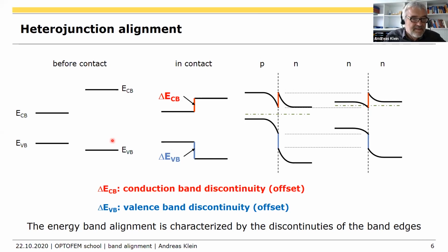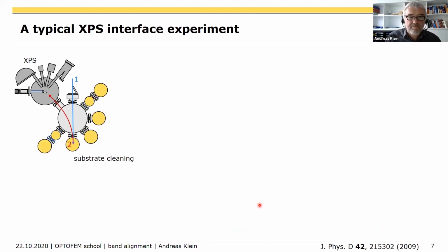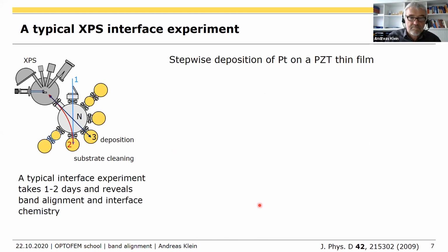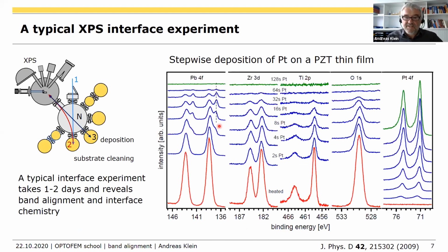Question by Pamela: on slide 7, what is the approximate thickness of platinum to induce a clear reduction of lead? Well, slide number 7. It's here. You see, this is 4 seconds of platinum deposition. I would guess that's less than 1 nanometer. And it's not a chemical kind of reaction, so you don't need much platinum.